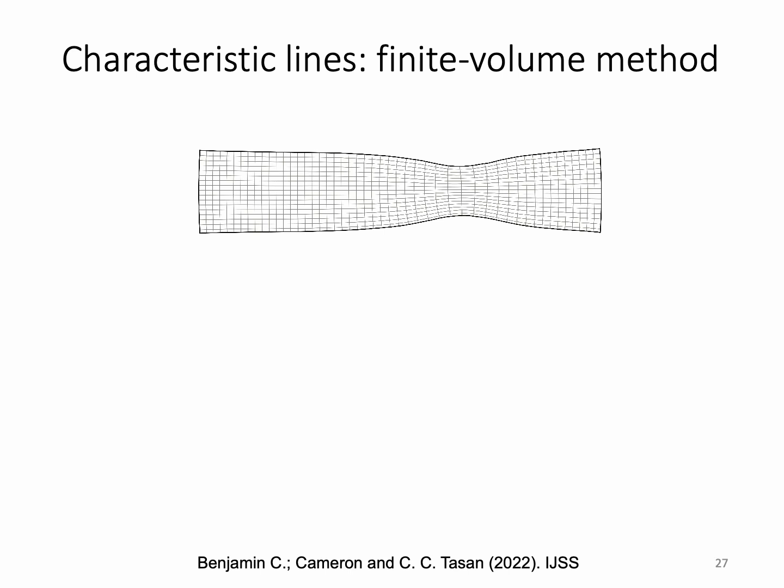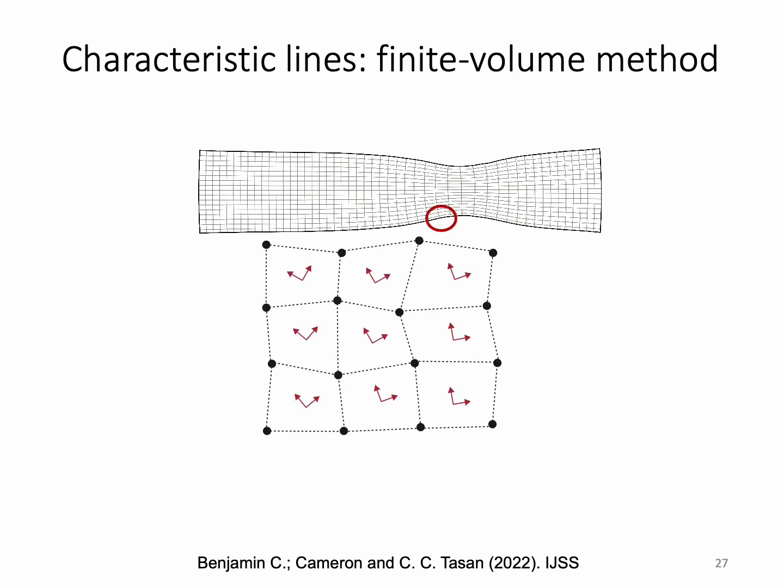And instead of chopping up the domain according to the characteristic lines, which can introduce a little bit of error, we just arbitrarily chop up the domain into finite volumes. In each element, we calculate the principal directions, and we assign a direction of computation. And it's very important to assign the directions of computation consistently. Otherwise, it's really easy to get singular matrices, etc., if you don't do everything perfectly. So this code was published as well, so it's freely accessible.